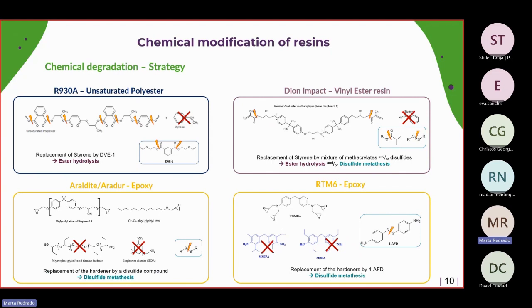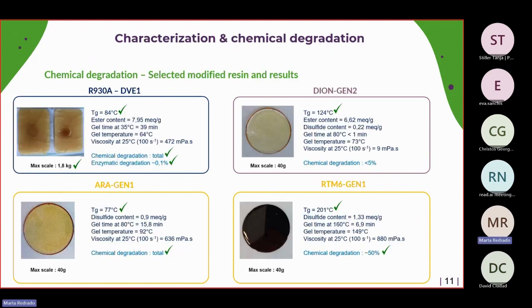So in the field of the resins, we studied 4 different resins in the project: 2 epoxy at the bottom, an unsaturated polyester and a vinyl ester. The idea is to introduce reversible bonds into these structures, and the strategies that we followed for the unsaturated polyester and the vinyl ester are very similar: replace the styrene by DVE-1 in the case of the polyester resin, and by methacrylates and disulfides for the vinyl ester resin. For the epoxy resins, we replaced the amine hardener by disulfide compounds. The 4 resins were studied.